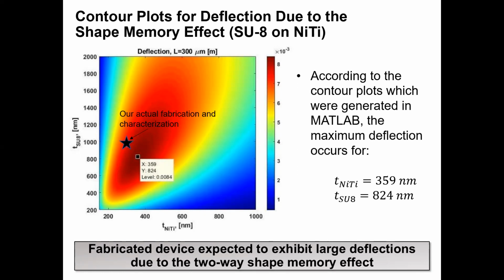So overall, these results motivated the fabrication of a much thinner NiTi beam, as would be suitable to undergo more significant deflections during the actuation cycle. You can also see here that the SU8 layer should be sufficiently thin, in this case around 1 micron or less, to also stay within the dark red region. So the predicted condition for max deflection due to the shape memory effect was determined to be 824 nanometers of SU8 on top of 359 nanometers of NiTi.